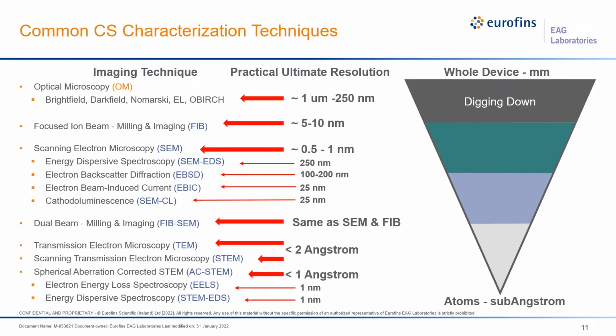And so that means that we need to do more destructive types of analysis where we have to do FIB lift-out and TEM of those materials to try to understand what's going on with the crystallography. And that gets us down to the ability, in the case of spherical aberration corrected STEM, or AC-STEM, we now have sub-angstrom resolutions for that kind of imaging.